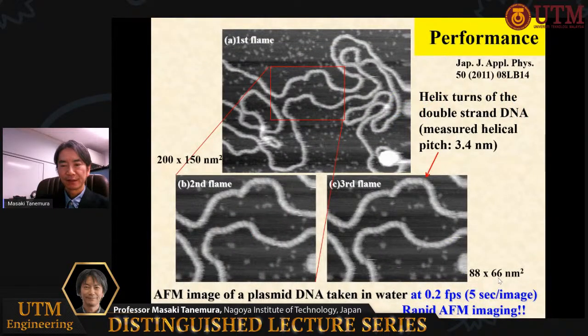This is the image of DNA measured in water. The scan speed is 5 seconds for this one frame. Usually, it takes a few minutes for one frame of imaging. So, this is a very rapid scan. They are the second and third images of the frame here. You can see the helix turns of the double-strand DNA clearly. So, the carbon nanofiber probe is very suitable also for the imaging of soft materials and biomaterials.